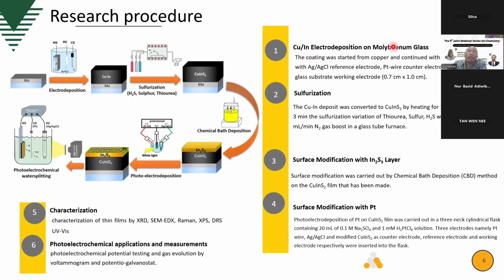So we use the molybdenum glass for a good back contact, usually for P-type. Some research uses FTO, but they have to cover it with silver or gold on the FTO just to make it have a good contact. The coating was started from the copper and continued with indium, using a three-electrode setup: reference electrode, counter electrode, and working electrode.